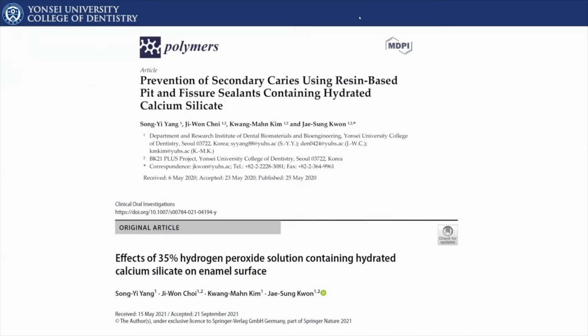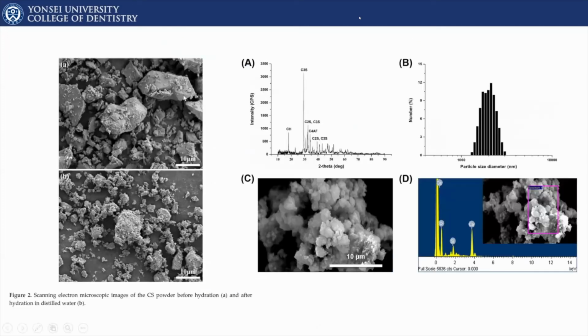So we wanted to investigate whether we can use the hydrated calcium silicate for resin-based materials such as pit and fissure sealants or tooth whitening agents. As you can see here, when the calcium silicate is hydrated, it has different appearances, which we analyzed with EDS, showing calcium and silicate-based structures on the surface of these materials.